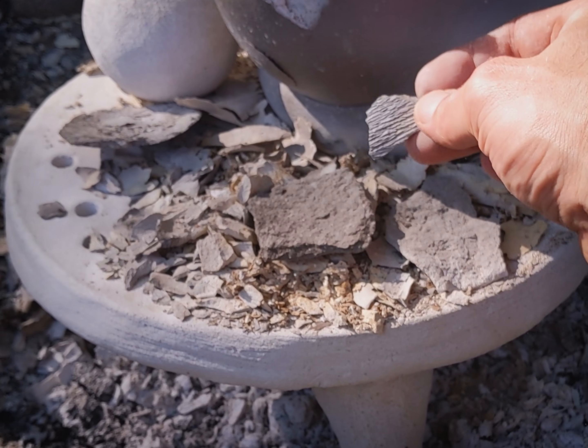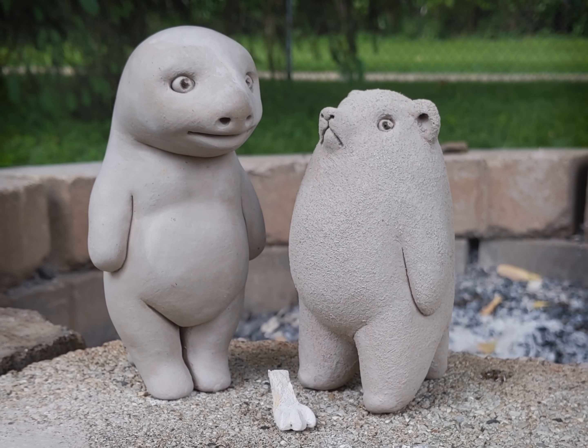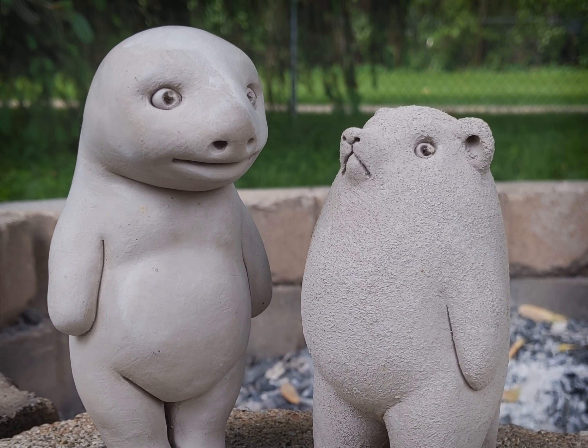The non-paper clay test subject exploded catastrophically. A foot is the only piece I recovered. So it got to a pretty good temperature, but next time I've got to move much slower through the first stages of the firing.